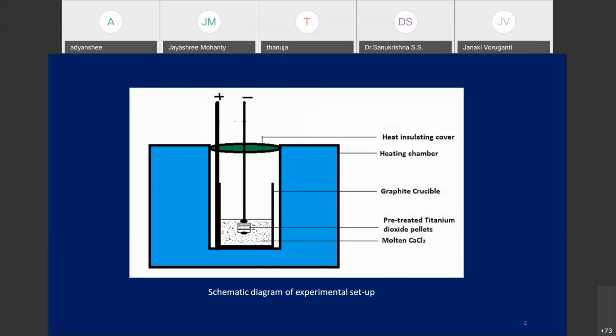That part is carried out because it is a fused cell electrolysis and we are producing reactive metals, so we don't prefer the presence of moisture or any kind of contamination of water. So it can be treated. Then you have to melt the calcium chloride. Usually the melting point of calcium chloride is 773 degrees centigrade, but it is not worthwhile to use the electrolysis process at this temperature. We use the electrolysis temperature basically at 950 degrees centigrade. 900 to 950 is sufficient.